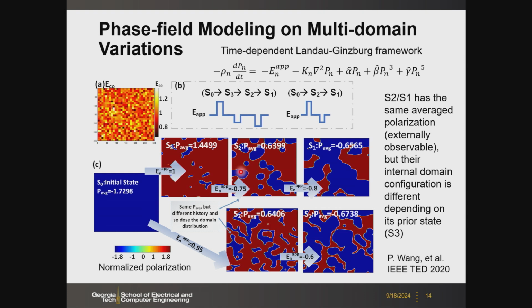Here we did some device modeling on this multi-domain switching mechanism using the phase field modeling approach. Essentially, we simulate the time-dependent Landau-Ginzburg equations, which are partial differential equations describing the interaction between the domains and the external field. The key thing is that we have to assume there are multiple domains, and each domain is different in terms of its coercive field, the critical voltage to flip the domain. Then we design those two loops, the larger loop and smaller loop, and run the simulations.